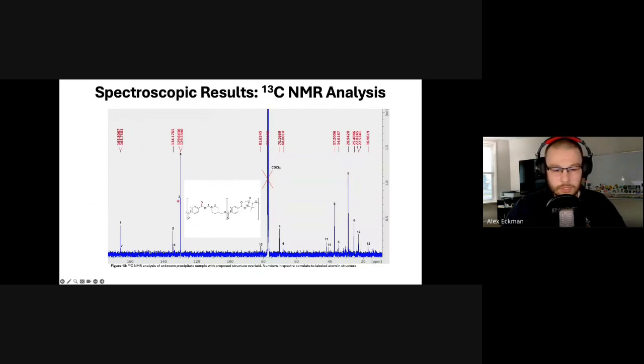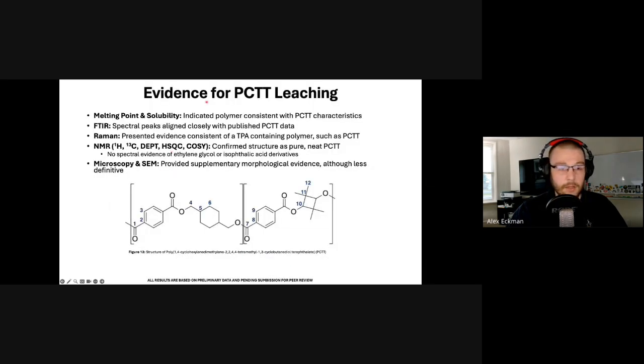What we were able to really use to definitively tell us the structure was a host of NMR analysis using 1D and 2D NMR. And right here, I just took a screenshot of our carbon NMR and went ahead and overlaid the structure with the numbers of these peaks representing what carbon we assigned on the structure. We also have a hydrogen NMR, DEPT, COSY, and then HMBC. But really, the NMR mixed with the other spectroscopic methods allowed us to pretty definitively say that we've got evidence of PCTT leaching in these brand new unused vape cartridges, which was certainly cause for concern and very interesting.